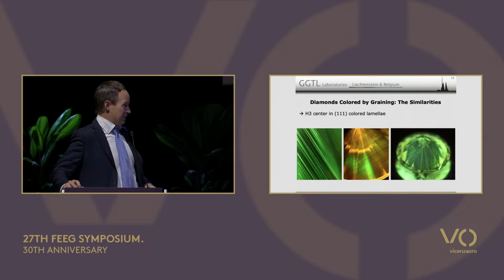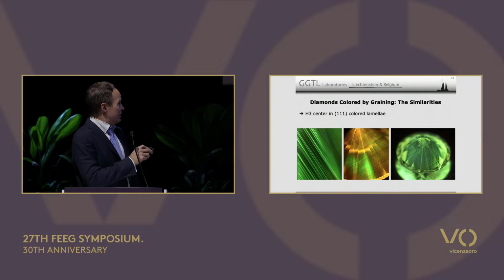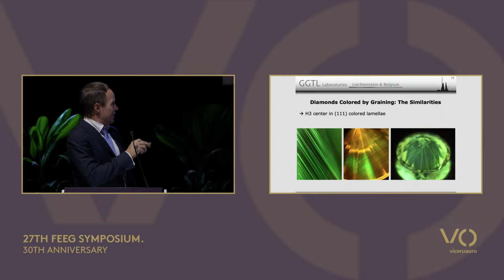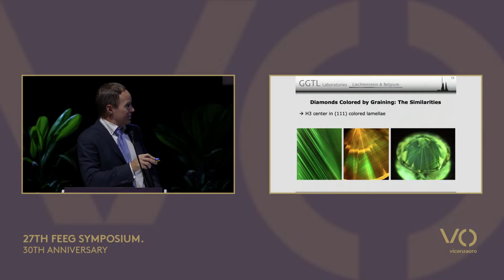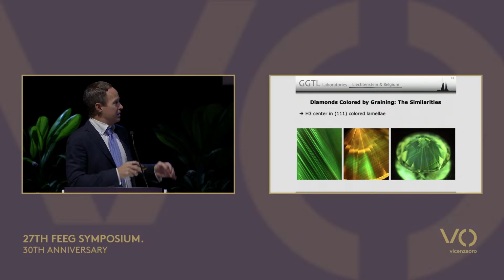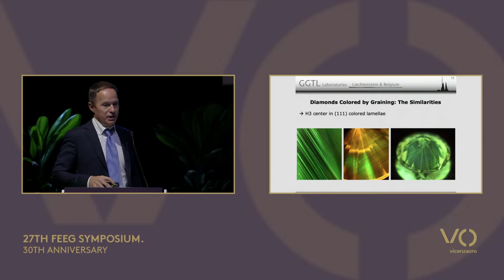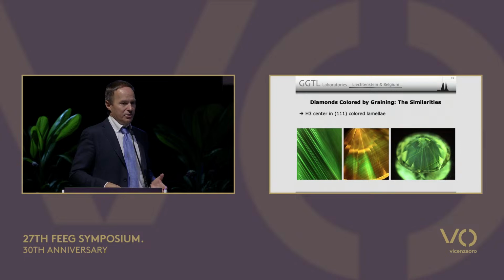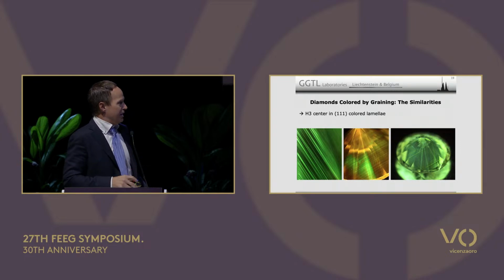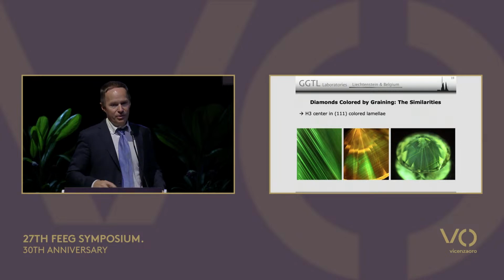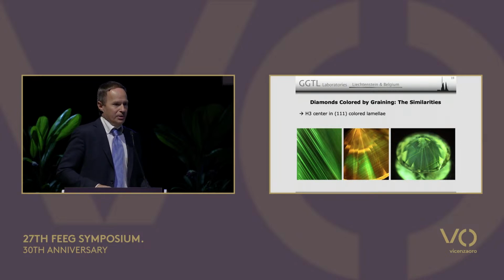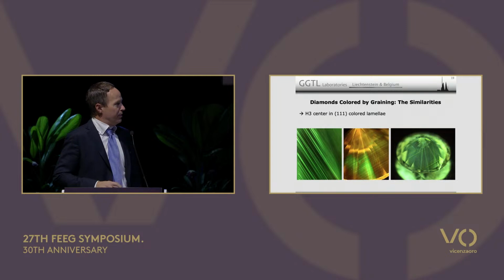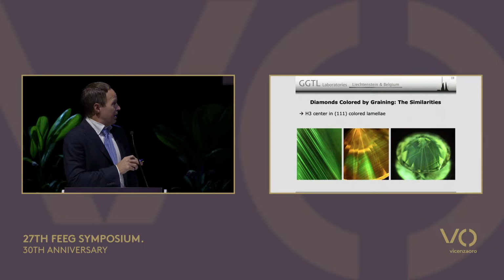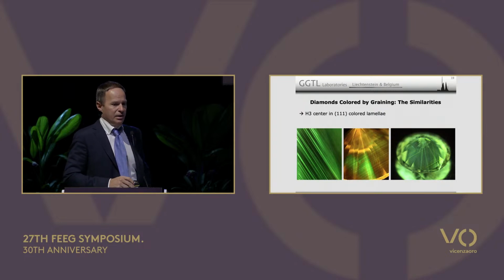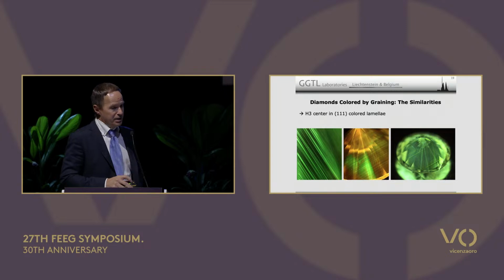Fluorescence. Here you can see the same thing. So these are basically the color lamellae that you see in those samples. And the fluorescence, as it is concentrated here, is from the H3 center, which is a nitrogen vacancy defect. So you can see that within those colored lamellae, you have very elevated concentrations of nitrogen vacancy defects. That's something you see in pink, brown, and olive diamonds, identically in all of them, this green fluorescence.